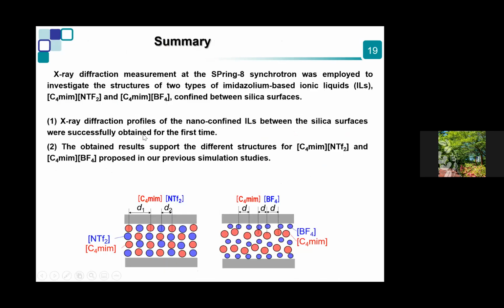So we can show that such X-ray diffraction is very effective for characterizing confined liquid, and the obtained results support the different structure for different ionic liquids proposed by our simulation studies. So if the ions are aligned in such a way, the distance between ions is quite different depending on the cases, so that we do not see any clear diffraction peak. But in this case, because of very clear organization, we see the peak.